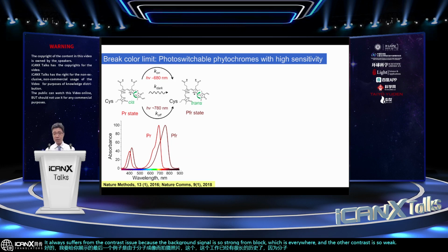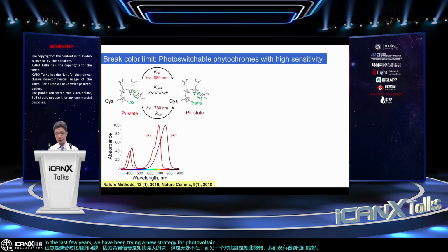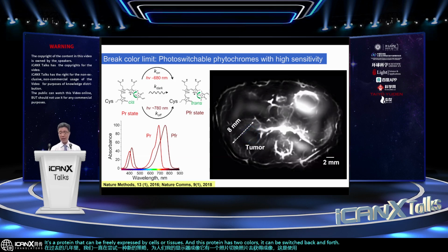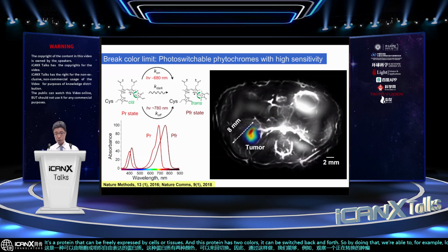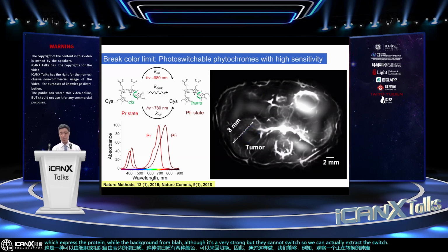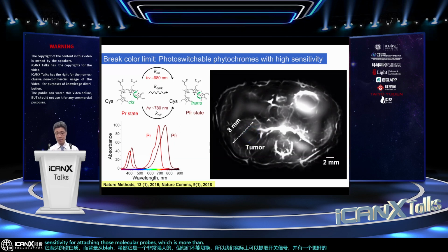In the last few years, we have been trying a new strategy for photoacoustic molecular imaging. It's called photoswitching photoacoustic imaging, which uses the photoswitch of phytochromes. It's a protein that can be freely expressed by cells or tissues, and this protein has two colors. It can be switched back and forth. So we're able to, for example, look at a switching tumor which expresses a protein, while the background from blood, although very strong, cannot switch. So we can extract the switching signal and have much better sensitivity for detecting those molecular probes, more than 1,000 times better than traditional photoacoustic imaging, which relies on a non-switching mechanism.